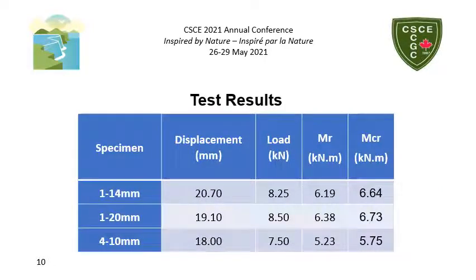All the 3 rebar configurations presented similar results for maximum displacement, load, and cracking moment. The maximum displacement ranged from 18 to 21 millimeters, the maximum load from 7.5 to 8.5 kilonewtons, and the cracking moment ranged between 5 to 7 kilonewton meters. It is worth mentioning that the code calculations performed in accordance with CSA A23.3 and CSA S806 matched the experimental data, and the moment capacities from the code proved slightly conservative.